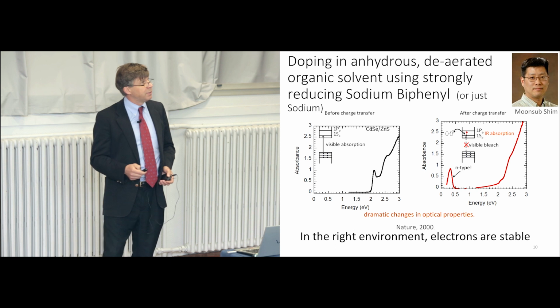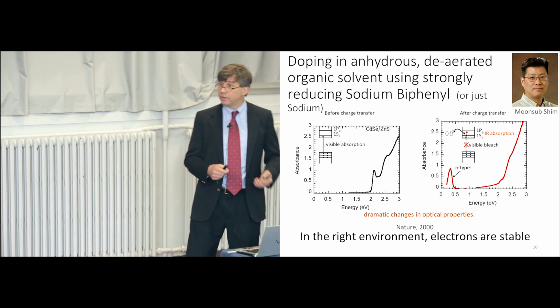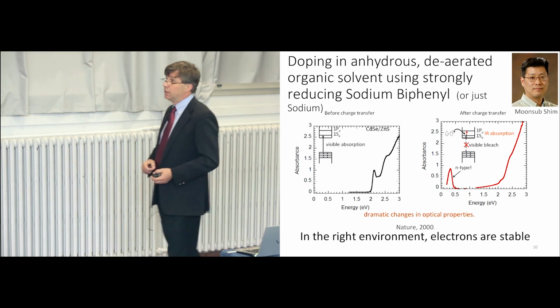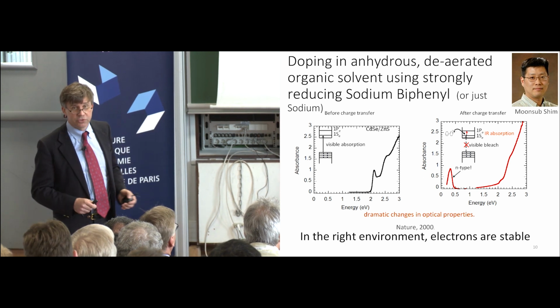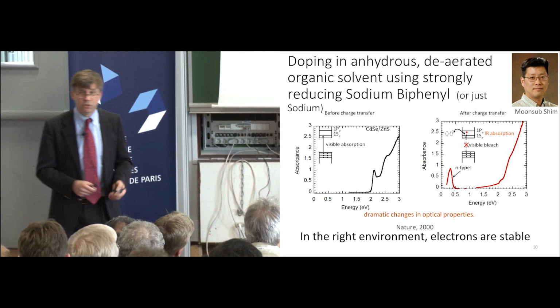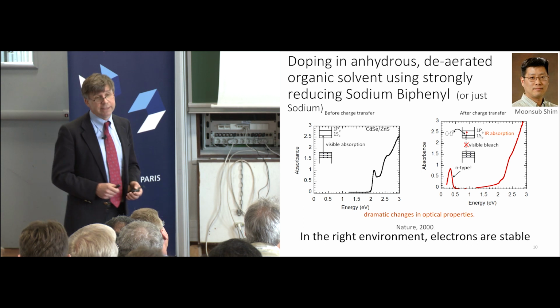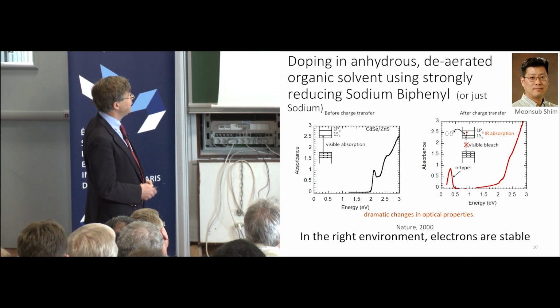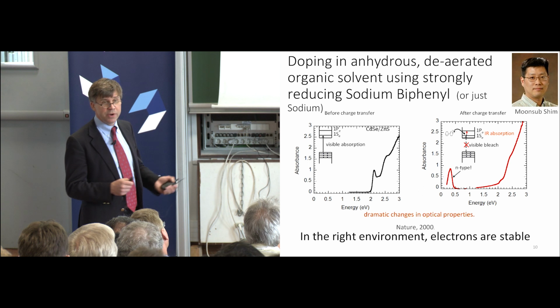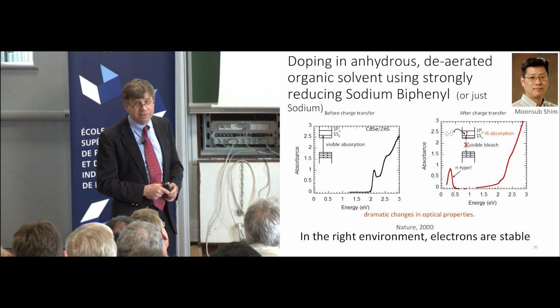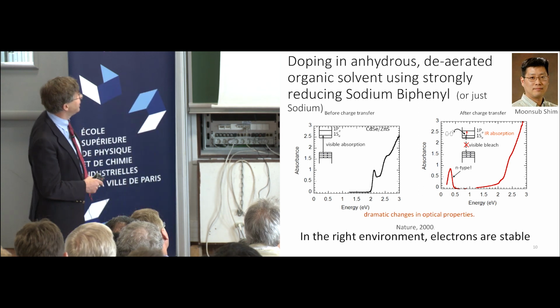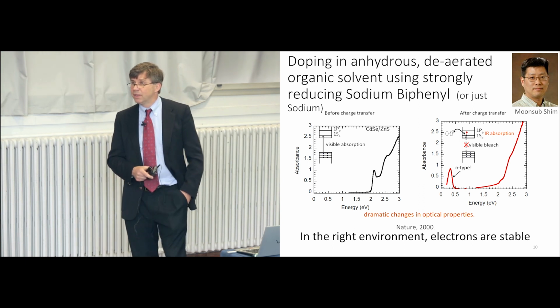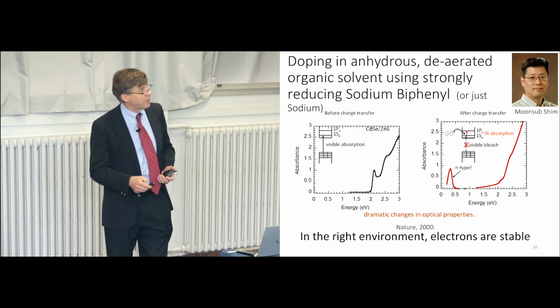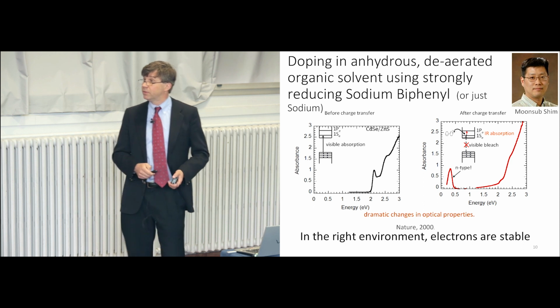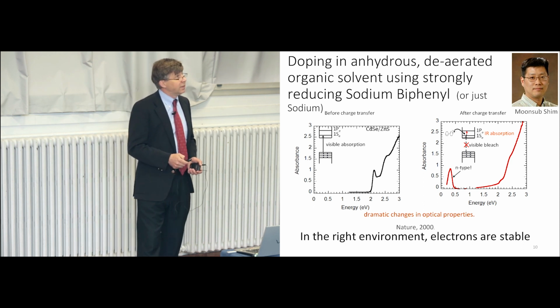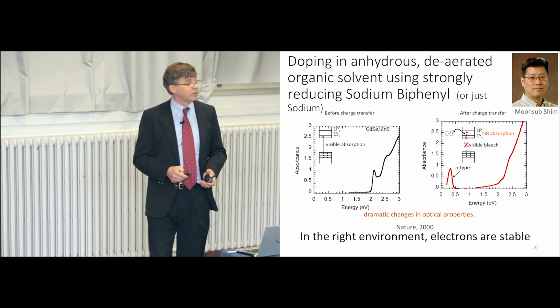And this was done by Moonsub Shim. We were looking for ways to inject charges in quantum dots. And I told him, well, just take a chunk of sodium, put it into your test tube, and look for the spectrum. And he tried that, and it didn't work. But he's very smart. And one morning, I come back and he says, you know, I saw something interesting. I used sodium biphenyl and put it into the test tube, and I saw this beautiful infrared absorption. And he discovered the way of charge transfer doping a nanocrystal.